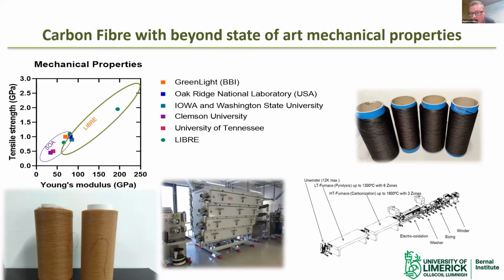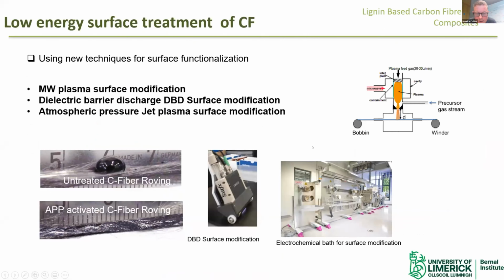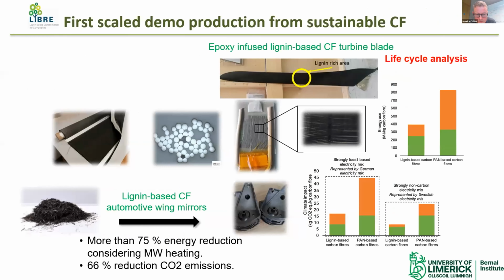These are the type of properties that you can deploy in wind turbine blades. Not only did we produce these mechanical properties, we were also able to scale these fibers. You can see images here. This is the precursor fiber before it's carbonized, and over here this is the carbonized. It turns black after you carbonize it. Once we produced the carbon fibers, we did some surface treatment, and this work was done at my colleague's lab, Dr. Ida, in the Fraunhofer in Bremen, where he did some surface treatment using microwave plasma, dielectric barrier surface modification, and atmospheric pressure jet plasma. So we did the surface treatments before we deployed them in the composite materials, before we deployed them in matrices.